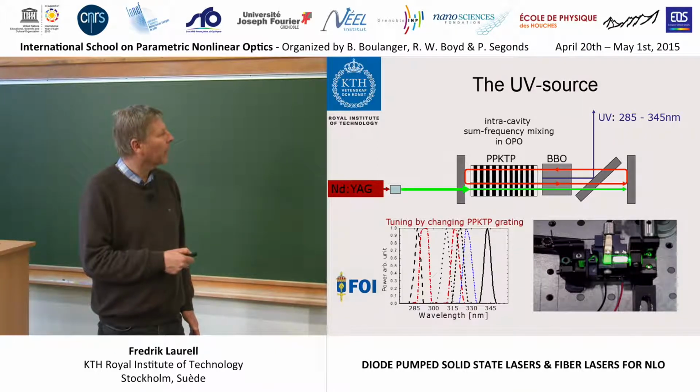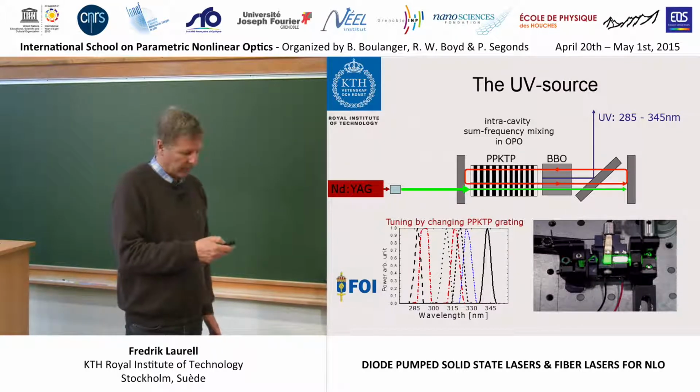And by changing the grating of the nonlinear crystal, which in this case was PPKTP, which operates easily in the visible at high intensities, then we can get all of these wavelengths here. And you can see how compact this system was.